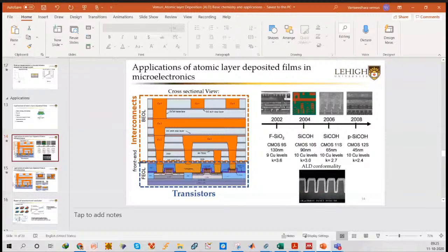One is this deposition, like ALD as well as molecular layering, is it always multi-layer or do we have monolayer also being used in the applications? That is a good question, Vasan. So we never use monolayer because, as I said, monolayer sometimes could lead to islanding problems. So we use multi-layer. Multi-layer meaning we do at least 2 or 3 cycles to make sure that the surface is covered. Okay. So initial reaction mechanism would be different.